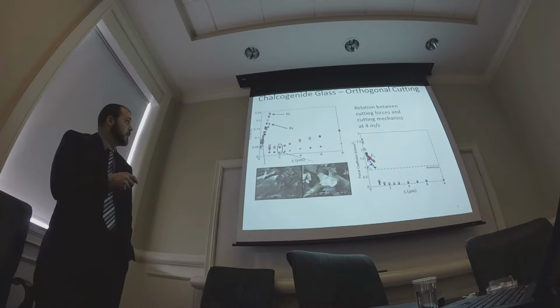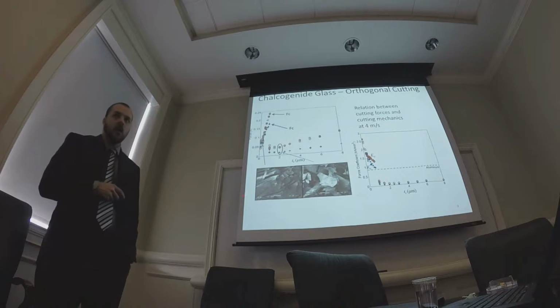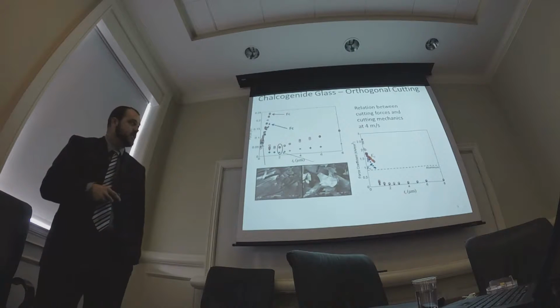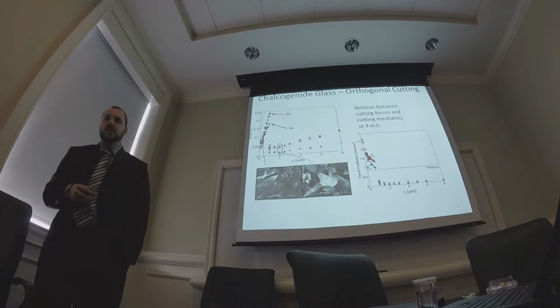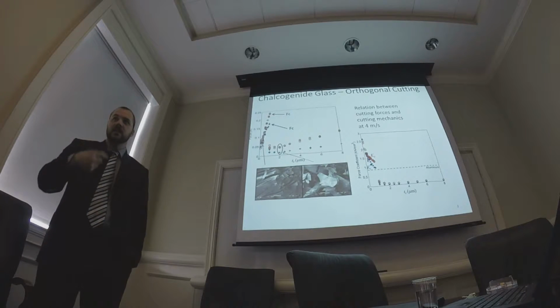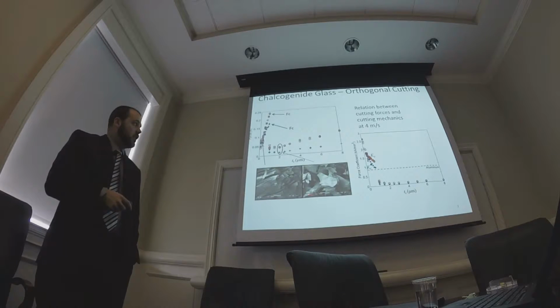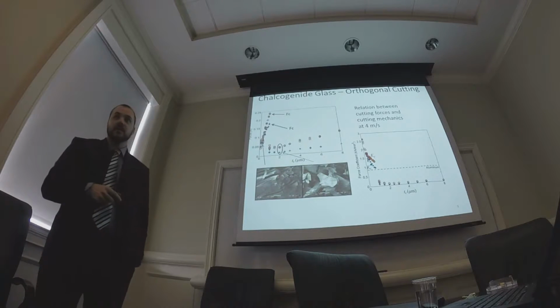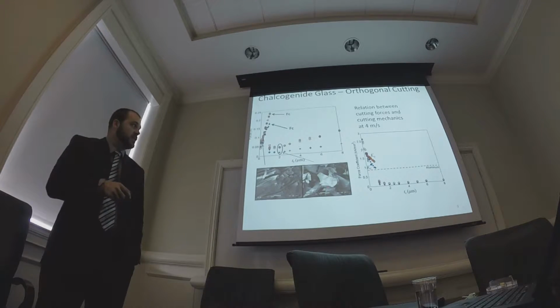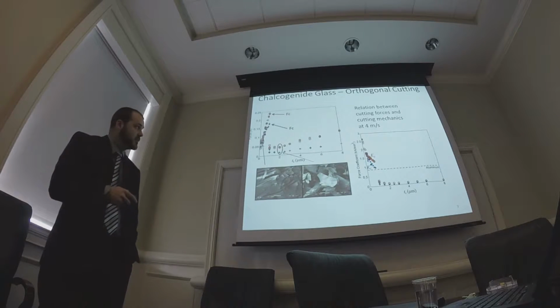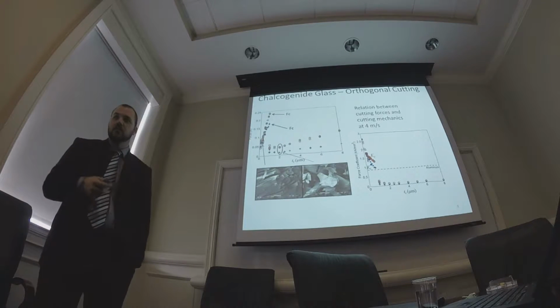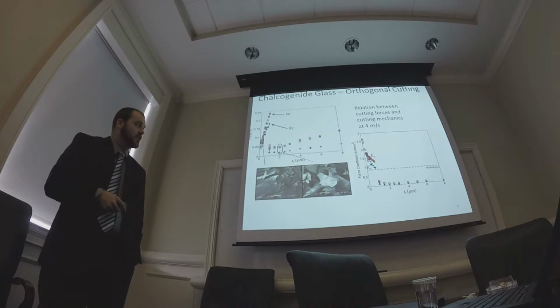So we found some chips from this test and from this test here. And the chips here, we see these curly 200 micron long curly little shavings. This is something I would expect to see when you're sharpening a pencil or something - nice and curly shavings. And then here, I looked all over trying to find anything that looked like this for these chips, and all I found was pieces that look like gravel, with that stereotypical fracture-like striation marks. I don't remember what they're called, but so brittle and ductile dominated.